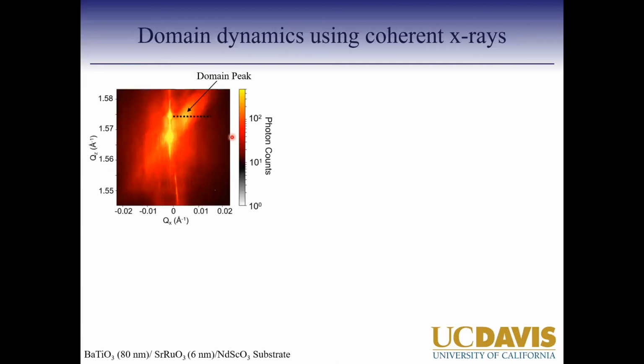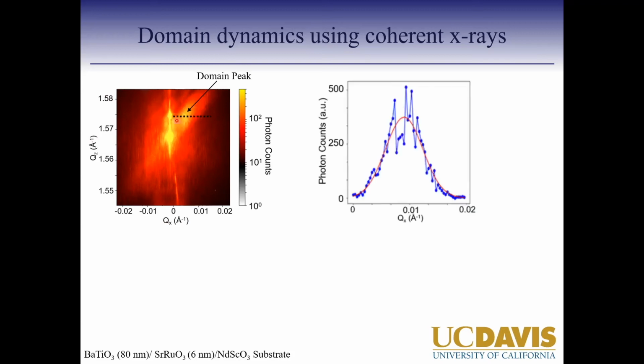So this is the normal Bragg peak right here from the sample. And because we have an ordered structure, an ordered A and B peak, because of that ordering, we see a domain scattering peak very close to the Bragg peak. And we can look at this domain scattering peak. You can take a cut across, and that cut looks very speckly, and that's coming because of coherent X-rays, which if you didn't have, it would look like a red Gaussian. So if I look at these speckles along this cut, I can start to map how these speckles are moving as a function of time.